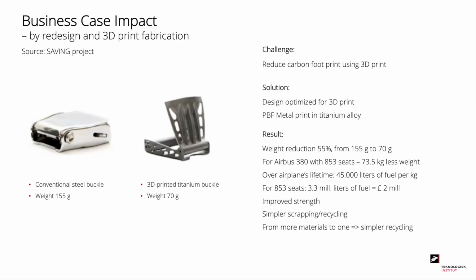And it has been calculated that over an airplane's lifetime, each kilo contributes to a fuel consumption of 45,000 liters. For the 853 seats, that means that the 73.5 kilo weight reduction reduced the fuel consumption by 3.3 million liters, corresponding to a saving of 2 million pounds over the airplane's lifetime. In addition to that, you have improved strength and you have simpler scrapping or recycling at the end. So we go from several materials to just one. So that's a simpler recycling.